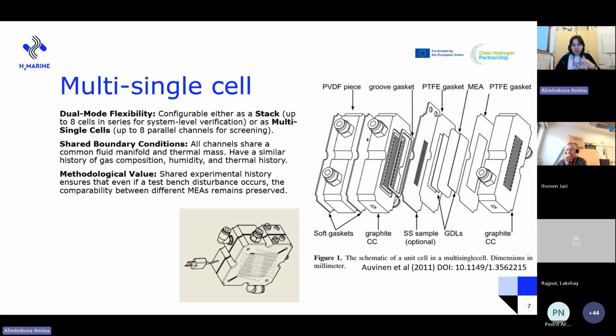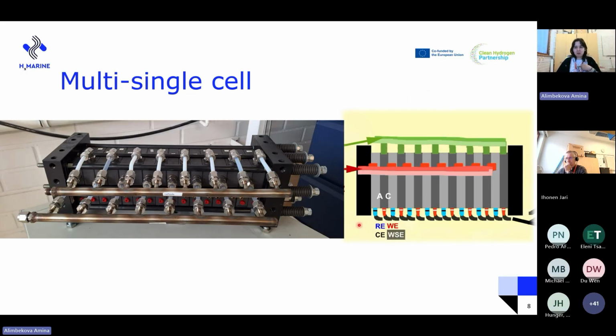As you can see from the 3D models here and also the physical photographs later, the multi-single cell addresses these limitations by offering a dual mode where you can use it as an 8-cell stack or 8 single cells, for high-throughput screening of independent MEAs using a shared mechanical fixture. As you can see here on the picture, when operated in this multi-single cell configuration, it gives us a very big methodological advantage where we have a consistent experimental history within the stack.